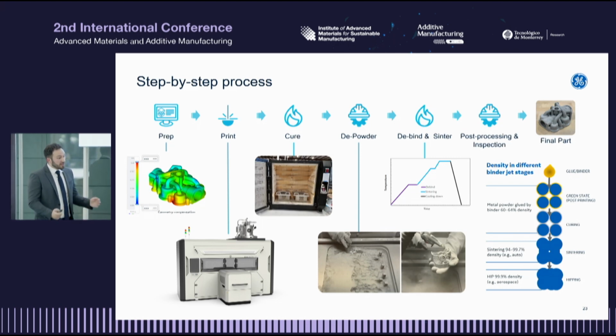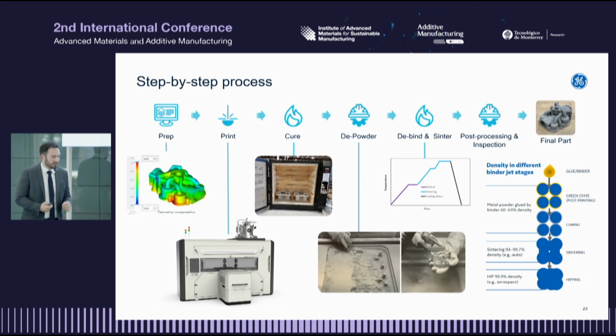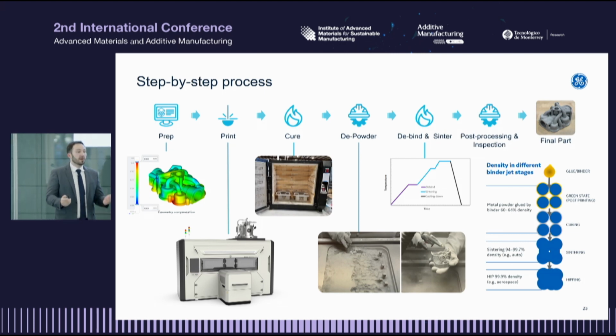So if you're less familiar with binder jet than you are with the laser process or even electron beam, just a quick layout of the methodology to go through and create a part. It is certainly the most complicated set of post-processing of all of the additive techniques. They come out in what we call a green state, so it's just powder that's glued together, and it needs to be subjected to a sinter cycle.